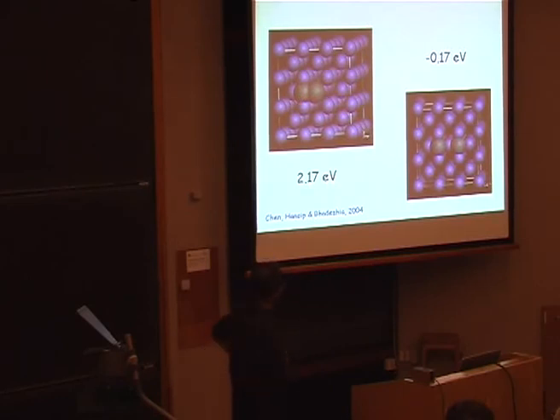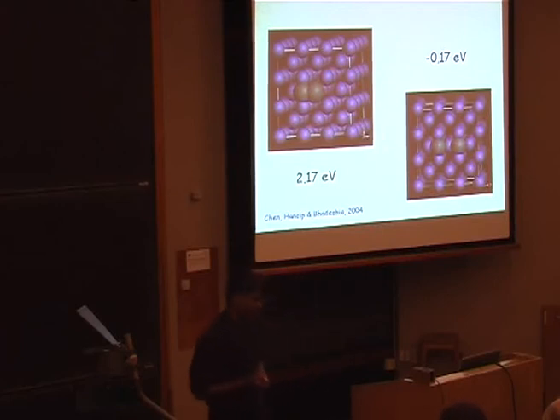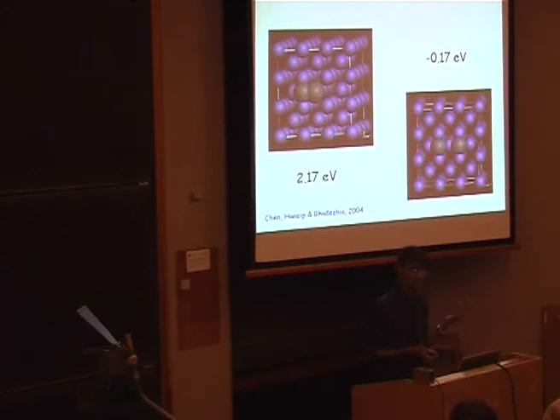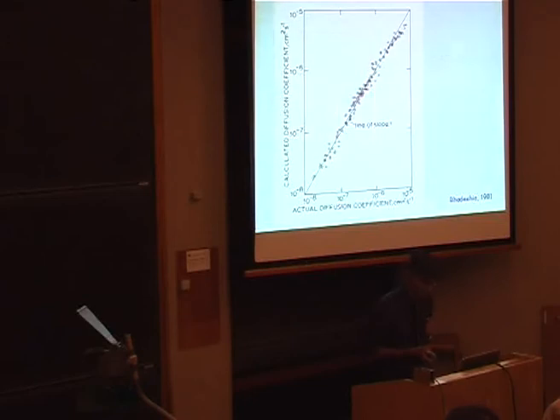And then we bring them together, either in the nearest neighbor or second nearest neighbor positions, and sure enough, we get this huge repulsion between those two carbon atoms, so we can put that into the thermodynamic theory and essentially exclude all the near neighbor sites from occupation. And we also correctly predict a slight attraction when we put these two carbon atoms in second nearest neighbor sites. So there's first principles calculations making a contribution to steels, which is the most used material in the world.